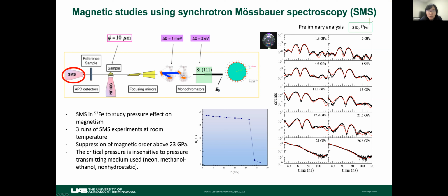You can see here, as you increase the pressure, the oscillations are suppressed. That's an indication of suppression of magnetism. The red curve here is just a very preliminary analysis using one single iron site. By fitting this data in CONUSS, we can extract how the hyperfine field is changing with pressure. Roughly based on the 3 different runs, we observed above 23 GPa a collapse of magnetic order. Again, this is taken at room temperature. This critical pressure of 23 GPa is also insensitive to pressure medium. Whether it's neon, methanol-ethanol, or non-hydrostatic, we always see a collapse of magnetism above 23 GPa.